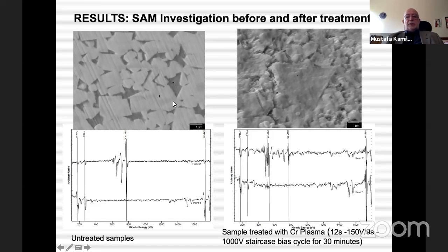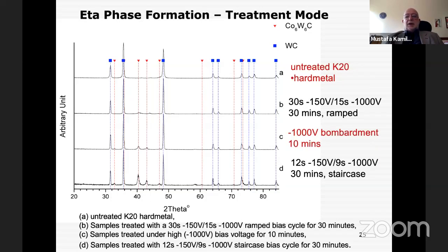This is the original surface. These dark areas are the cobalt phase, the light areas are tungsten carbide phases. So these are the scanning Auger analyses that were taken from these spots. When we alloy the surface, we found out that finally these areas where cobalt is present also have chromium in their structure. So it seems that we managed to alloy the cobalt phase with chromium. Another interesting output that we didn't expect to see was the formation of eta phase during this process.